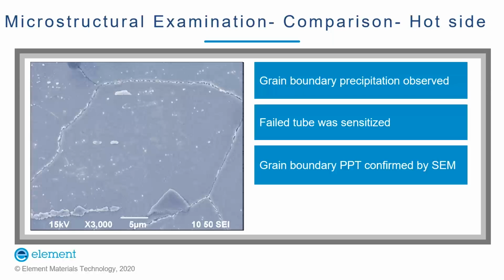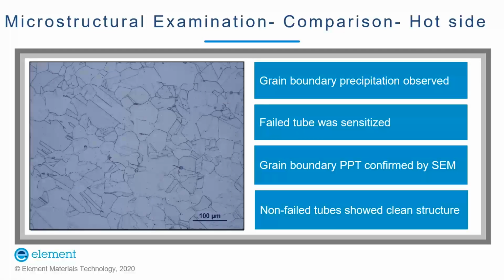We have done chemical composition analysis using energy dispersive spectroscopy, in short called EDS, which is attached to our SEM. These EDS results are presented in our next slide, but we will go back to the non-failed tube, which shows a very clean microstructure, and there was no evidence of cracking and precipitation in this tube. This suggests that, for some reason, the failed tube was subjected to an improper manufacturing process. Most likely the tube was subjected to improper annealing temperature or cooling rate during its fabrication.